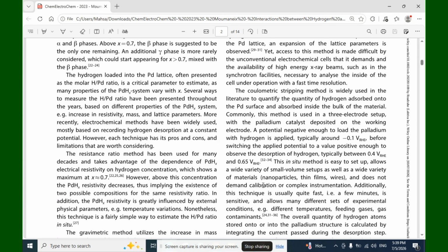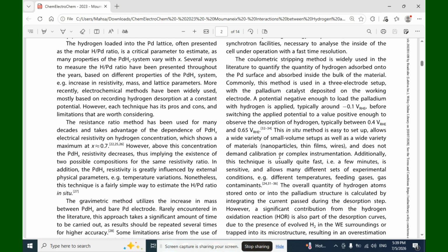This in situ method is easy to set up, allows a wide variety of small volume setups as well as a wide variety of materials, nanoparticles, thin films, and wires, and does not demand calibration or complex instrumentation. Additionally, this technique is usually quite fast, for example, a few minutes, is sensitive, and allows many different sets of experimental conditions, for example, different temperatures, feeding gases, and gas contaminants. The overall quantity of hydrogen atoms stored onto or into the palladium structure is calculated by integrating the current passed during the desorption step.